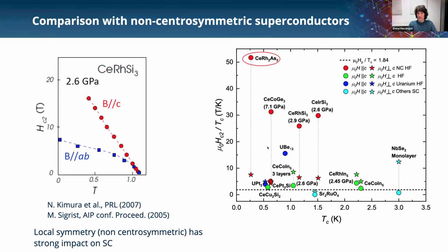Okay, and so here on the right, we have compiled a collection of a number of unconventional superconductors, very famous ones, where we plot the critical field normalized by Tc versus Tc. And we differentiate fields along C-axis and fields in the plane. And in red are all the non-centrosymmetric superconductors. So you see they all fall into this scheme of this strong anisotropy. And CeRh2As2 also falls into this scheme.